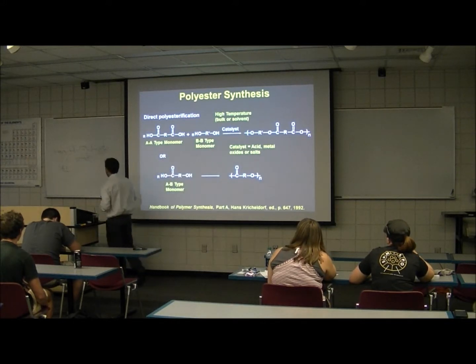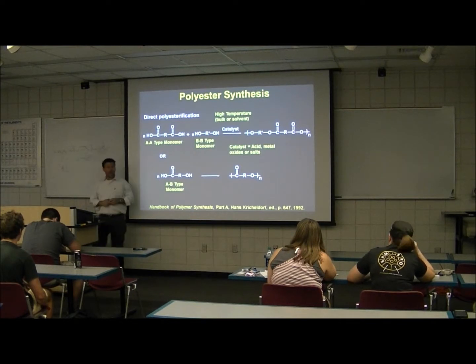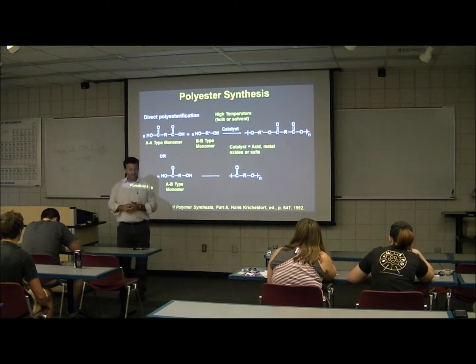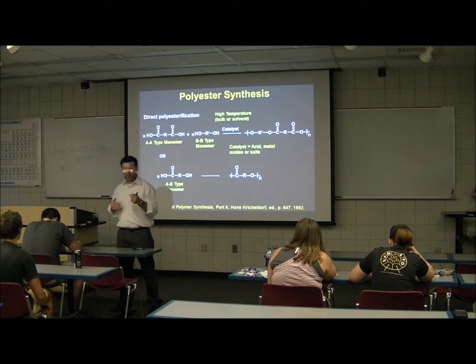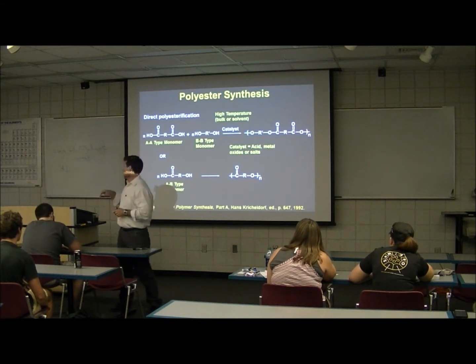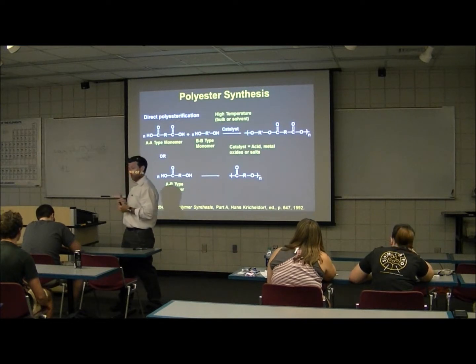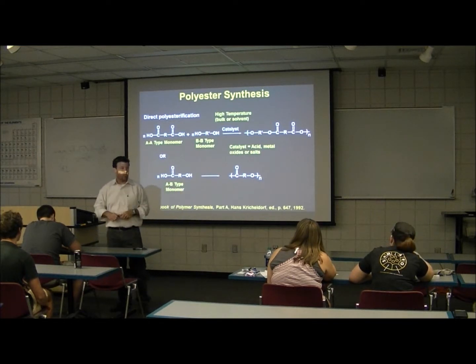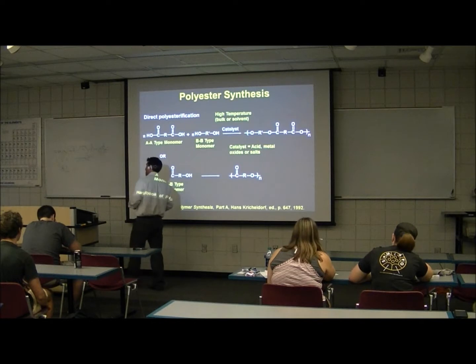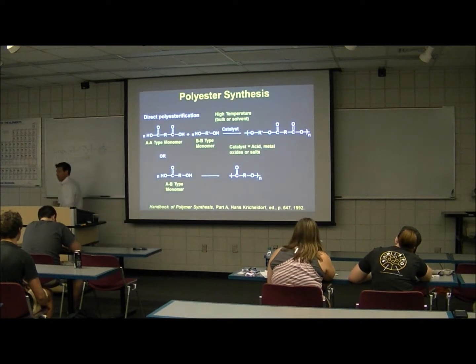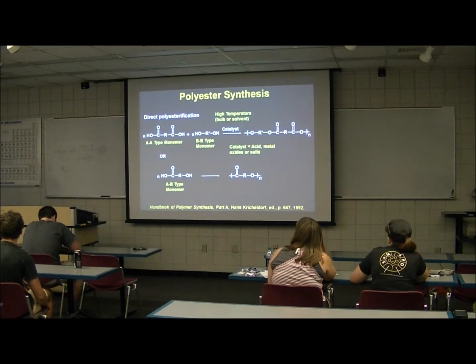So the tin is a horrible catalyst if you're going to do aliphatic systems, because there's 2 reasons we take systems to really high temperatures. One is we want to do it fast. And 2 is the monomers aren't soluble, so we have to use temperature to make things homogenized. Terephthalic, isophthalic acids are just not soluble. And you'll see this when we make polyester on Monday. We'll use terephthalic acid or isophthalic acid probably in a blend.